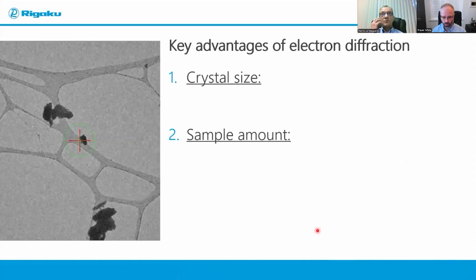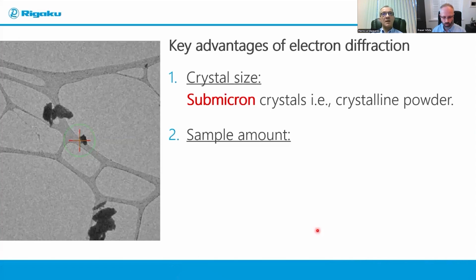And as a result, electron diffraction has 2 very important features: the crystal size that you can analyze and the sample amount that you need to actually go ahead with an electron diffraction analysis. So like I just said, crystal size, you can now analyze submicron crystals. But think about what that means. That means that you can do single crystal crystallography on a crystalline powder. Even when you're stuck with a precipitate and can't crystallize your compound, if your powder or your precipitate is crystalline or crystalline enough, you should be able to measure diffraction data using an electron beam.